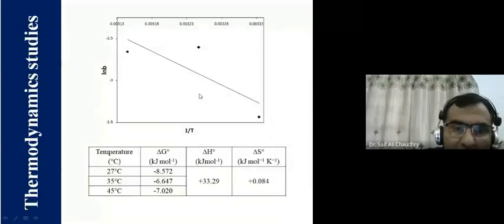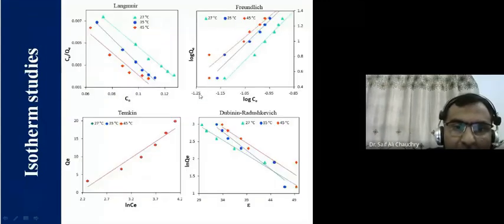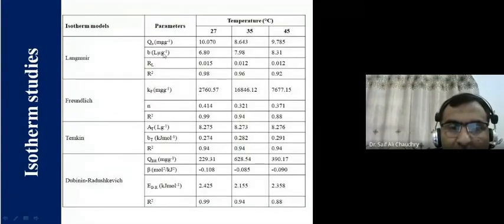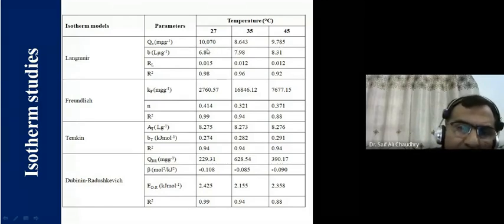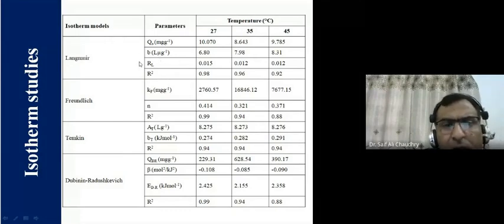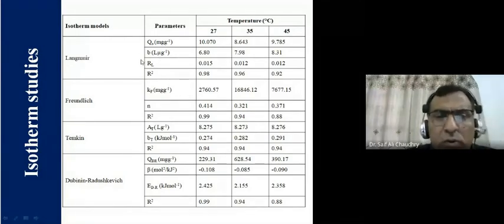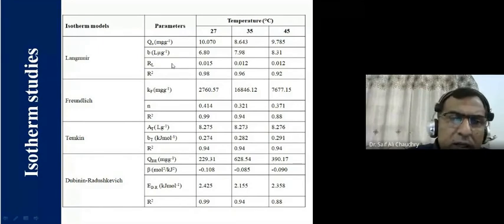Again, we have characterized and found varied parameters. Now, this material was not so good as compared to the earlier one. The Q naught value we got is 10, 8, and 9. It means the absorption of the dye molecule reduced with increasing temperature.